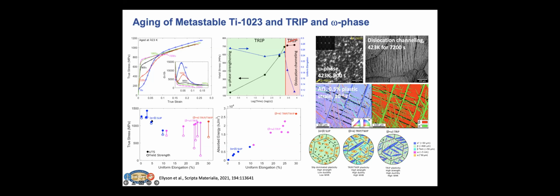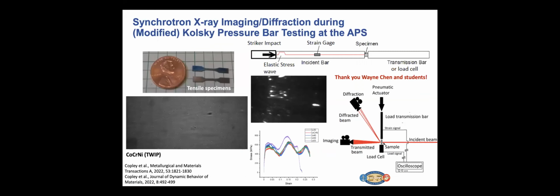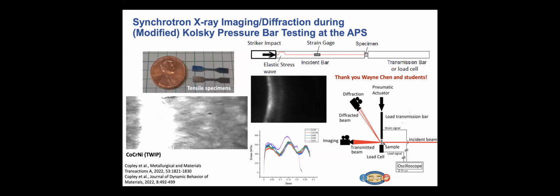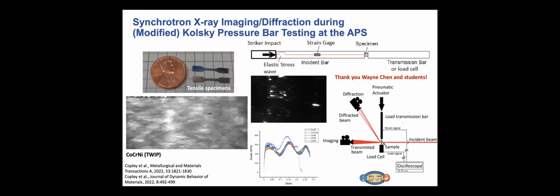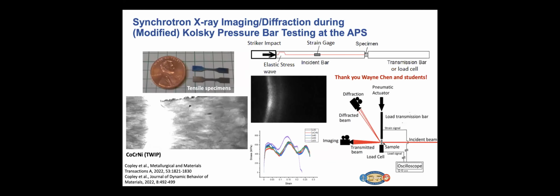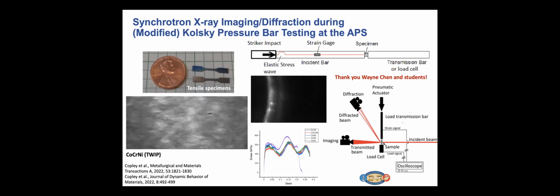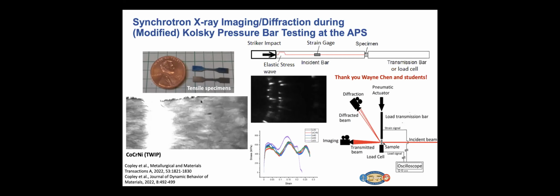For example, we can have the alpha and beta plus slip. We can have beta plus omega and TRIP, and then we can even add alpha phase back into the microstructure to enhance the strength a little bit. And so a lot of things can be done to manage the phase stability in the microstructures that we get. In this particular work, we actually were more interested in the dynamic properties of these materials. We were interested in absorbed energy for protective structures for DoD kinds of applications.